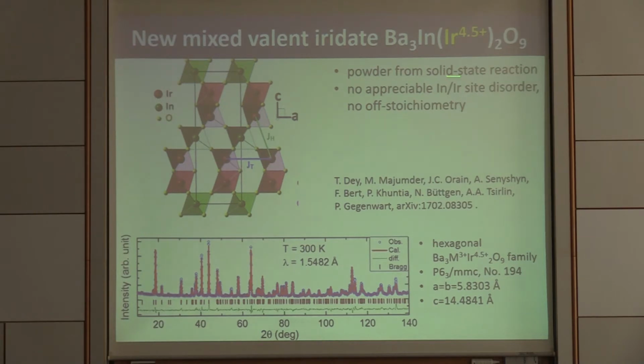First, this mixed valent iridate, where we have barium-3, indium, iridium-2-O-9. We recently synthesized this material. The XRD pattern is shown here. It's nice because there is no indium-iridium site disorder and there is no off-stoichiometry. And the magnetic properties of this structure emerge from these bi-octahedra, the iridium-2-O-9 units. And given the iridium valence of 4.5 plus, we see that there is one unpaired electron per such bi-octahedron. So probably we have some molecular orbital states where spin-orbit coupling needs to be introduced, and then there is an effective moment arising from this one unpaired electron.